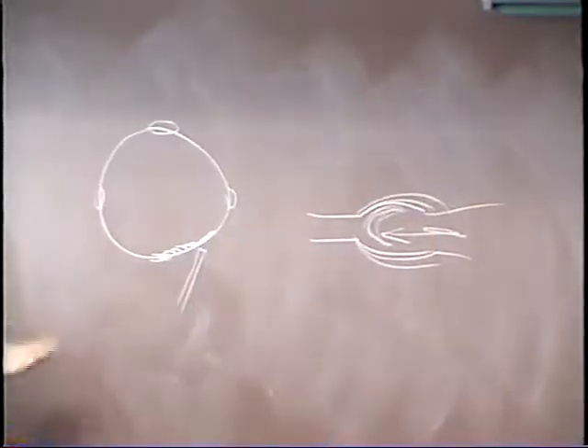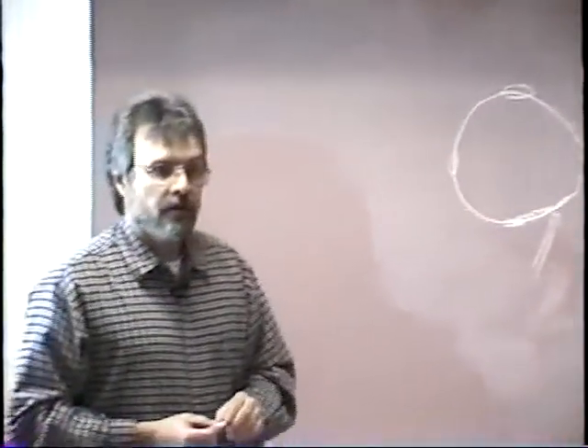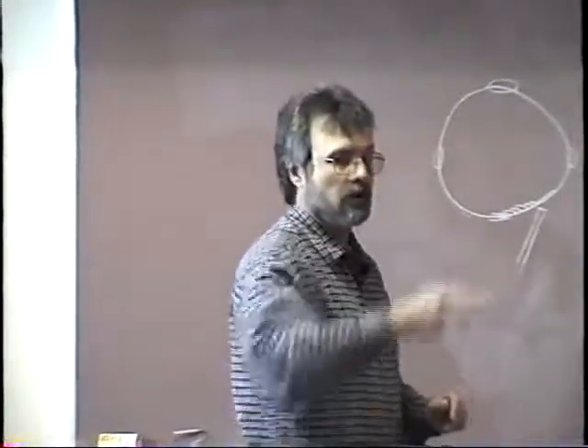And usually when I'm welding pipe, that's about the only time I'll use a whipping motion. That and when I'm coming into a tack. When I'm coming into a heavy tack, you can use the whipping motion to preheat that tack before you get there, and that will help you tie into it too. And that's with 60-10, right? Yes, that's with 60-10. Now there is a page in this chapter that deals with depositing a root pass with 70-18, but we're not going to discuss that in this class. That's a special technique that some of these mines out here, some of these trona mines use. But that's not typically something we would do.